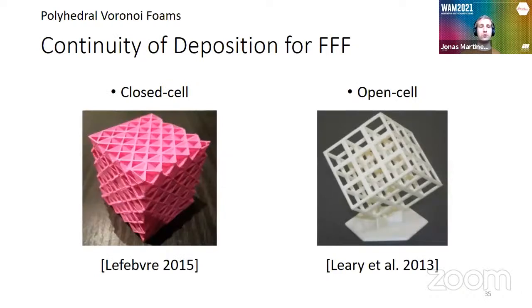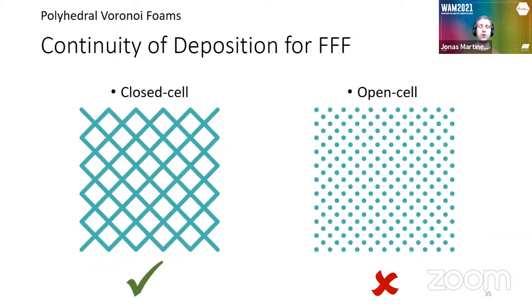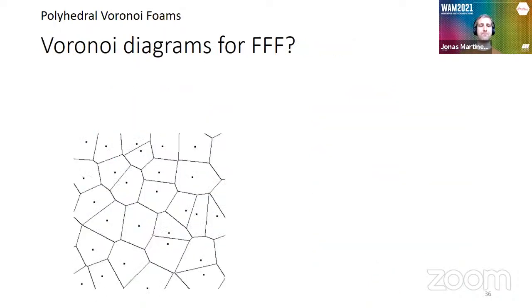So there have been different works on doing metamaterials, internal structures for fabrication. They can usually be broadly categorized as closed cell or open cell, depending on the kind of cell. We focus mostly on closed cell because the deposition trajectories are continuous when you look at the slice. The open cell is much more challenging because you have to travel the nozzle from one point to another, and this leaves spurious plastic things. So the first thing we thought was, okay, let's take the Voronoi diagram and apply it for fused filament fabrication. So here you have a 2D example.